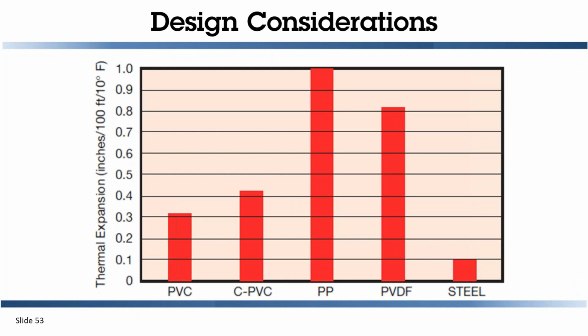One of the most important design considerations is the expansion and contraction of the piping systems. Plastic will expand far more than metal systems, and we can see polypro and polyethylene expand at a great rate of 1 inch per 100 feet per 10 degrees. That's about 10 times that of steel. For all plastics, we need to consider how it's going to react when you install it versus the operating temperature.